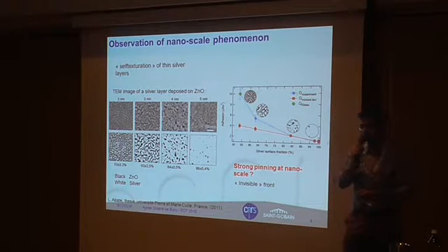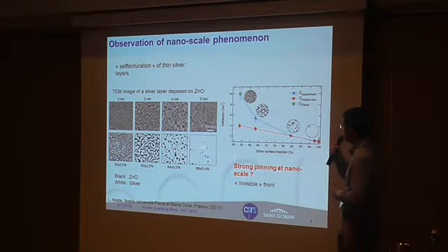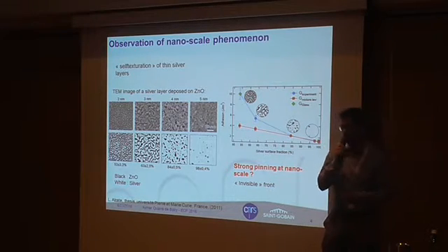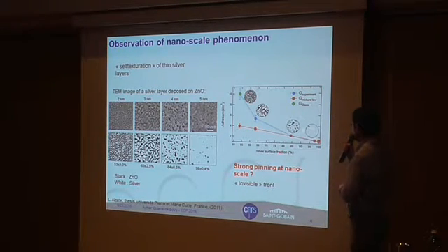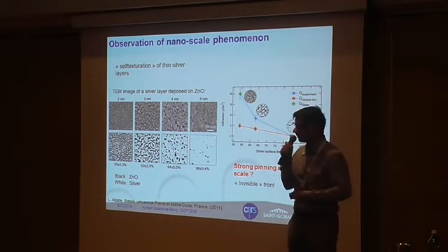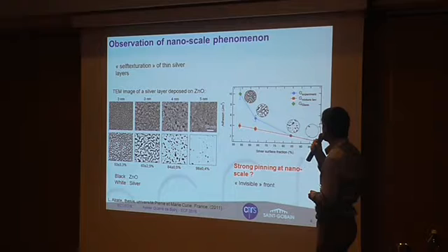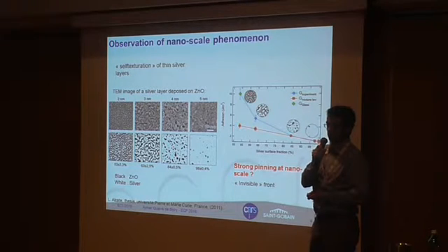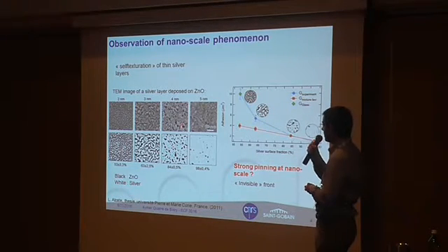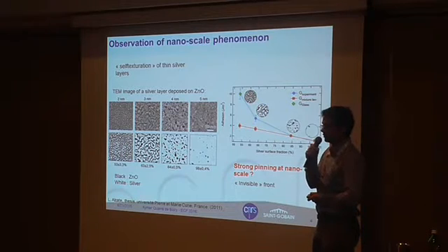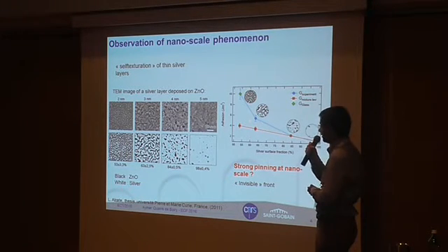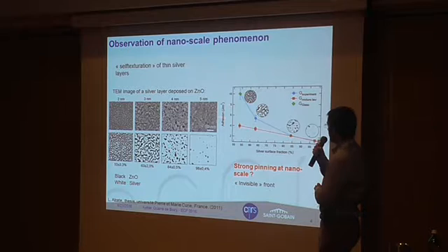With this type of self-texturation, we have a very large reinforcement of adhesion, because if we simply calculate the adhesion with a mixture law, by averaging the different adhesions, we don't get the measured adhesion, which is higher.